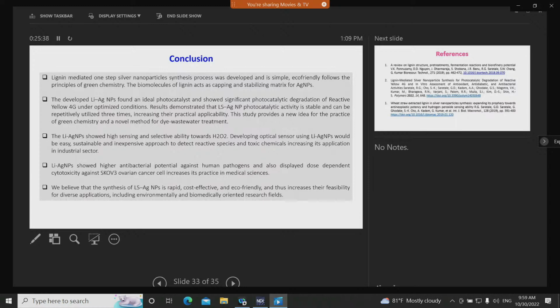The developed Li-Ag NPs were found to be ideal photocatalysts and showed significant photocatalytic degradation of reactive yellow dye under optimized conditions. And this photocatalytic activity is stable and can be repetitively used 3 times, increasing their practical applicability. In addition, this study provides a new idea for the practice of green chemistry and a novel method for dye wastewater treatment.